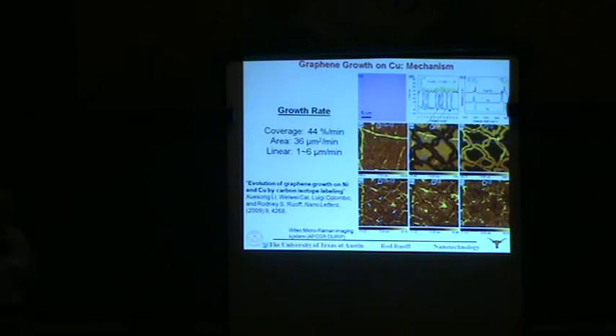So these wrinkles indeed appear because as we're cooling the copper, or it happens also for nickel and the other metals as well, at such a high temperature, the delta CTE, the coefficient of thermal expansion change, is quite large. And so the copper is contracting and the graphene doesn't want to. And so the stress buildup is such that it does de-adhere and you end up with these beautiful wrinkling patterns. I consider them to be beautiful for a couple of reasons. One is when we look at this material in scanning electron microscopy, the wrinkles are actually our way of identifying the presence of monolayer graphene before we go into Raman.